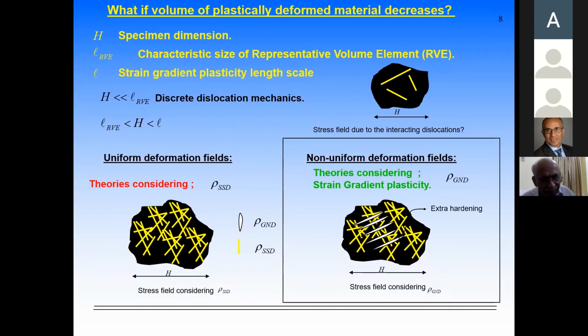The way we introduce this traditionally, because we consider yield stress is proportional to dislocations, but then when there is no length scale, those dislocations are called statistically stored dislocations. These are the regular dislocations that we know from theory of plasticity. But when length scale becomes an issue, then we call the additional dislocations geometrically necessary dislocations. These dislocations are created in order to accommodate the deformation. As a result, the smaller the sample, it will have a higher strength, stronger.